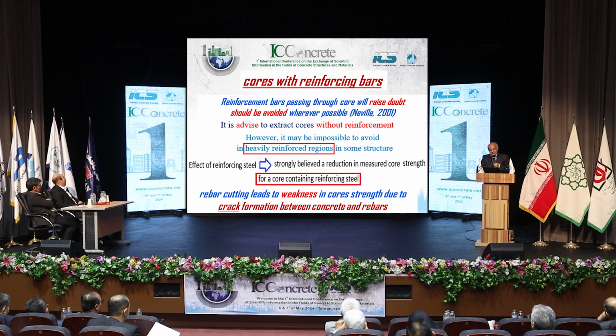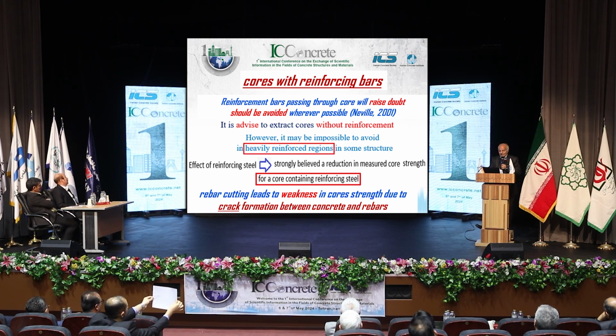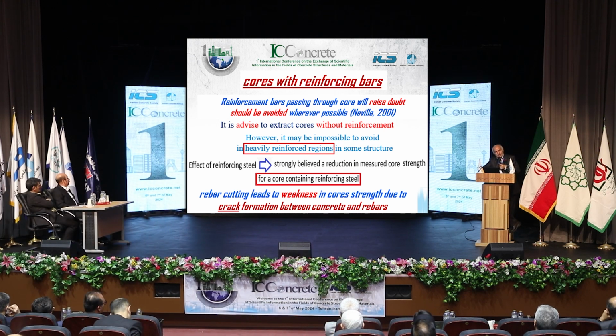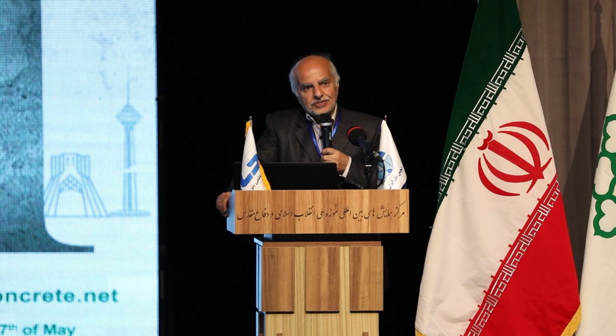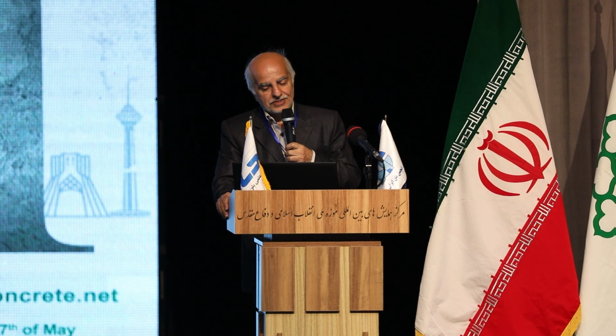But sometimes it might be impossible because of a heavily reinforced region, so you need to take into consideration the reinforcing bar in the core. I strongly believe that a reduction will appear in the core strength result, because rebar cutting leads to weakness in core strength due to the cracks forming between the concrete and the bar.